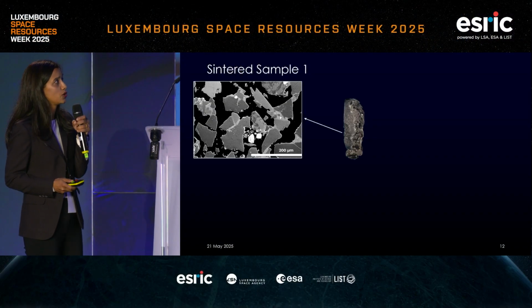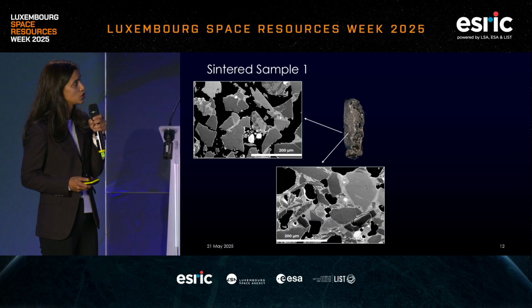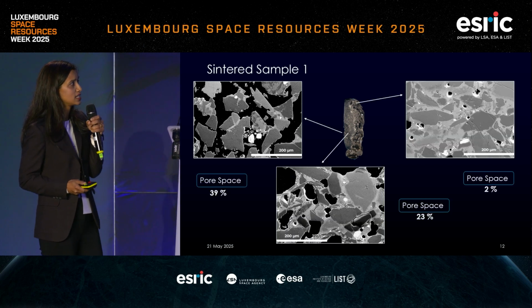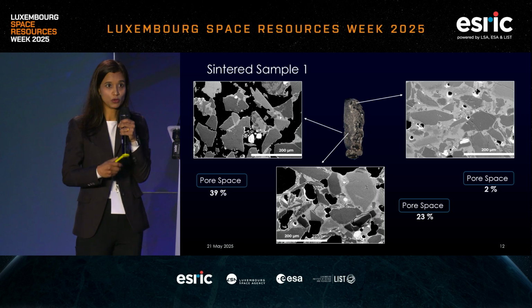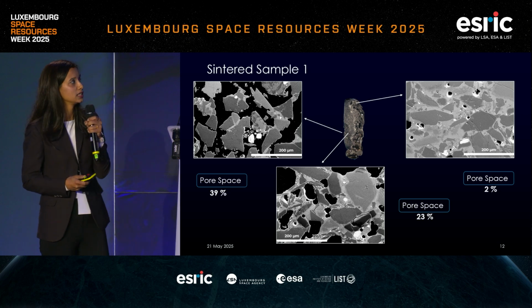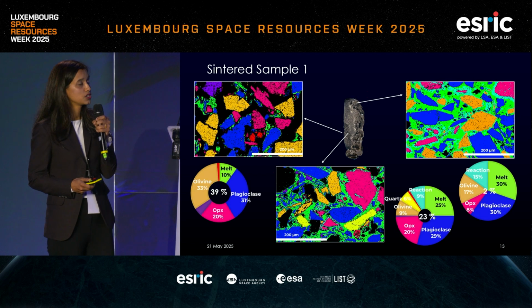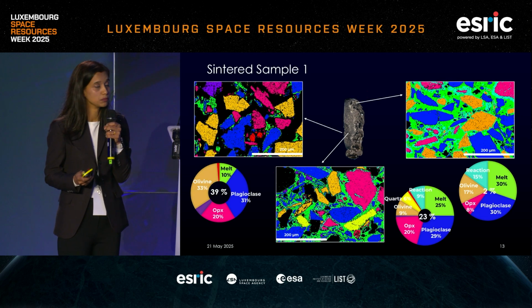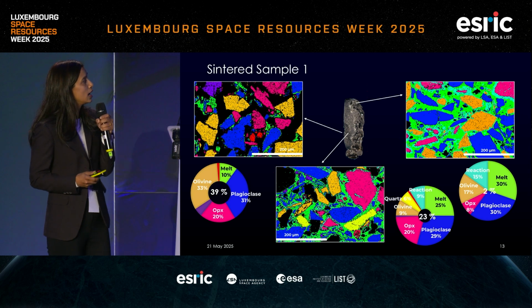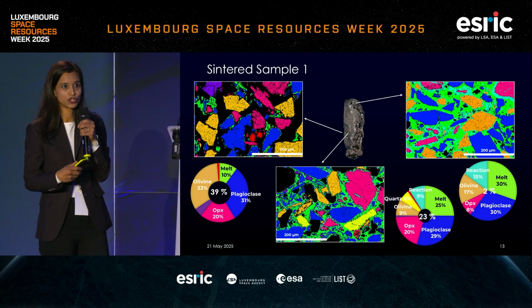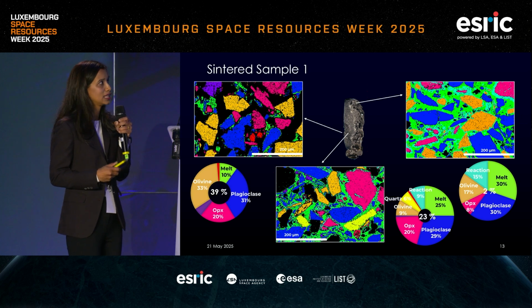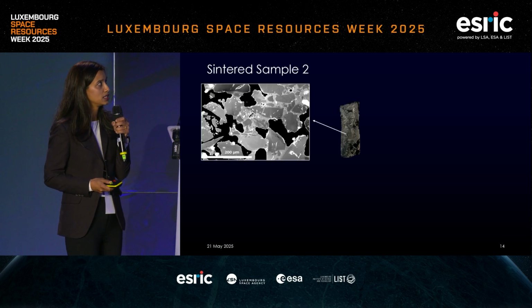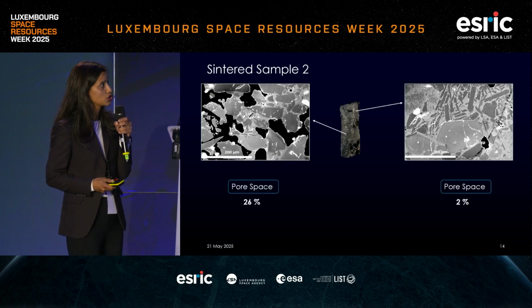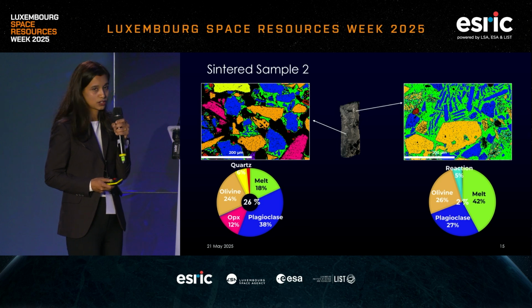So when we looked closer at these samples, for the first sample, we looked at the areas from these different zones, from the low temperature zone and the high temperature zone. We could easily identify the reduction in the pore space from low to high, indicating densification occurring in the high temperature zones. And when we did EDS mapping, we could, of course, identify the various minerals that we have in the lunar regolith simulant, but we could also identify the melt percentage, which you're seeing here in the green neon color, which helped us identify the low temperature and the high temperature zones. Similar observations were made for the second sample: low temperature to high temperature, pore space decreasing, melt percentage increasing.